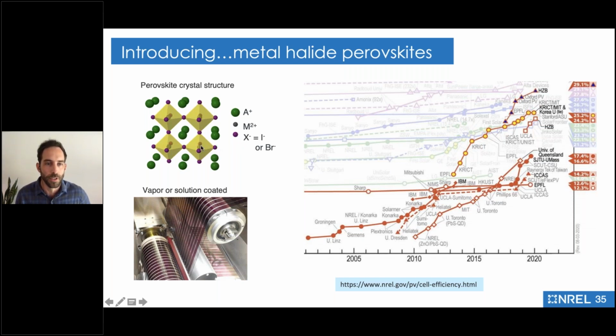And then on the corners of these octahedra are halides. So that's iodide, bromide, or chloride. So that is metal halide perovskites, and here's what people are excited about them. For one, they can be formed really, really easily. So people are now at large scales vapor and solution coating these things at very rapid rates.